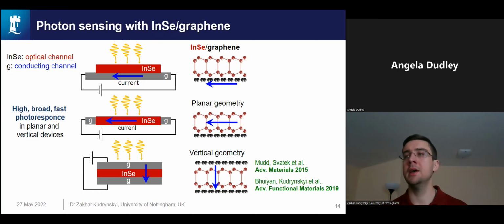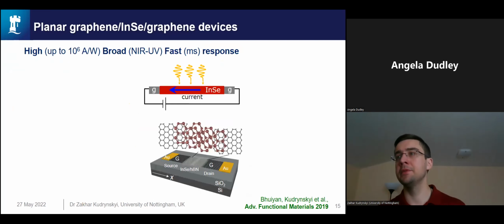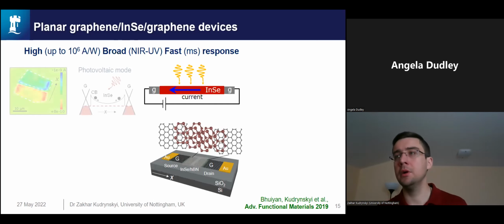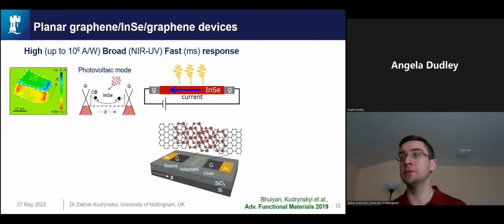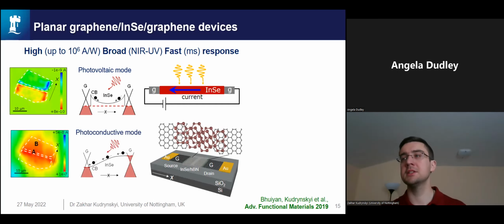So we have explored devices of both planar and vertical geometry. For example, this is a planar geometry where we have a flake that is on two graphene electrodes, and there are regions with partial overlap between the two layers, and there is a gap between the two graphene electrodes. So we can look at the photo responsivity of those devices. We obtained good photo responsivity even without any externally applied electric field. In other words, we see photovoltaic effect due to this bending at the interface. We can operate these devices in the photovoltaic mode, and they have very high responsivity.